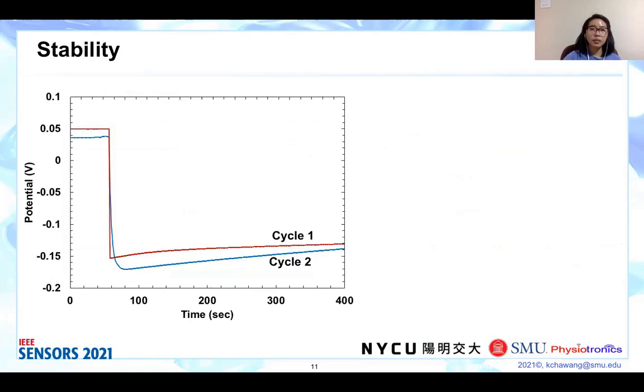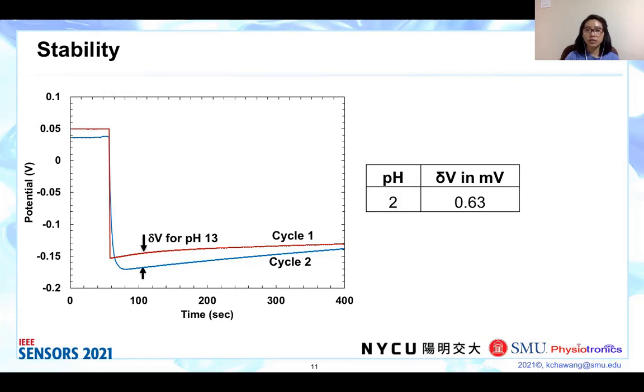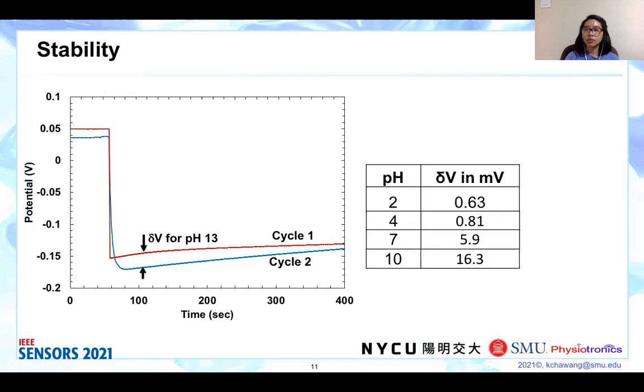Next is potential deviation. To study the potential deviation, we consider 2 cycles. Cycle 1 means tested in the sequence of pH 2, 4, 7, 10, 13, 10, 7, 4 to pH 2. Cycle 2 is a continuous test sequence from cycle 1. The plot shows the worst potential deviation, which is at pH 13. The potential deviation similarly at pH 2 is 0.63 millivolt, at pH 4 is 0.81 millivolt, at pH 7 is 5.9 millivolt, at pH 10 is 16.3 millivolt, and at pH 13 is 20.6 millivolt.